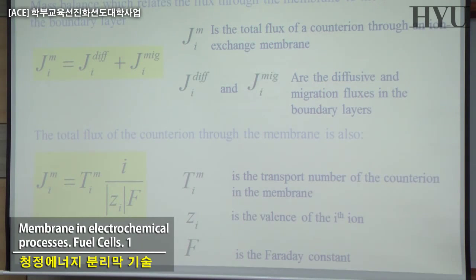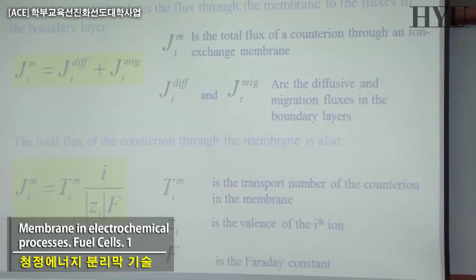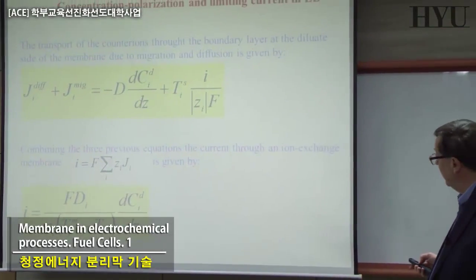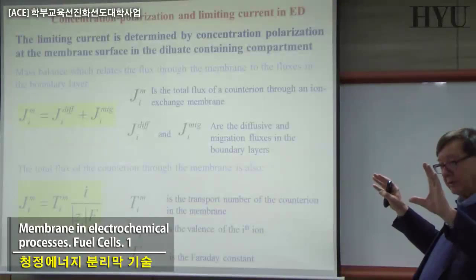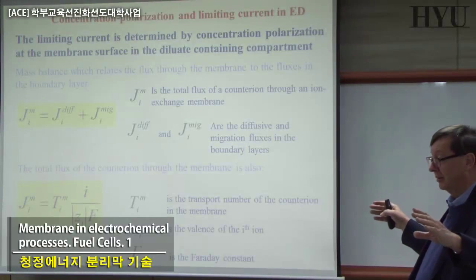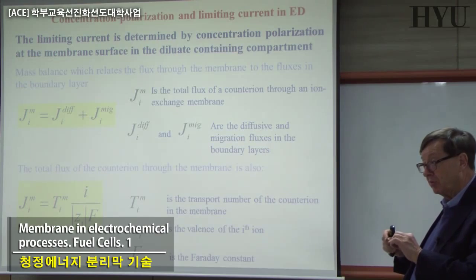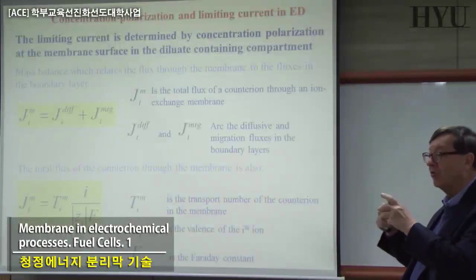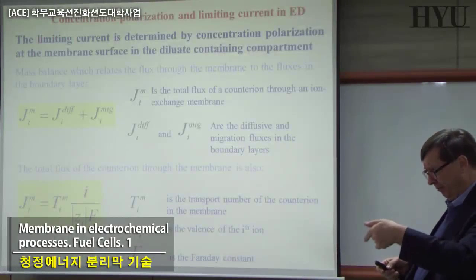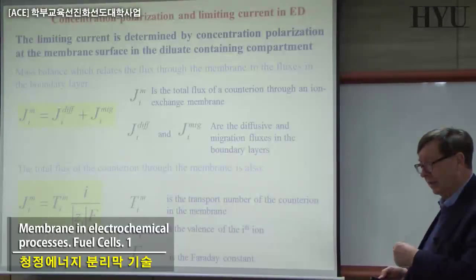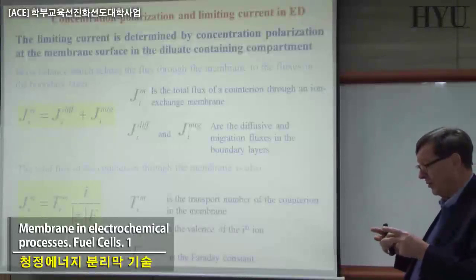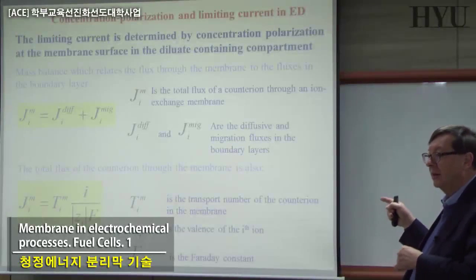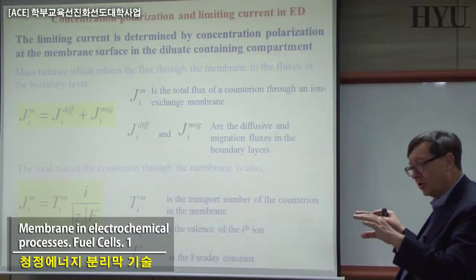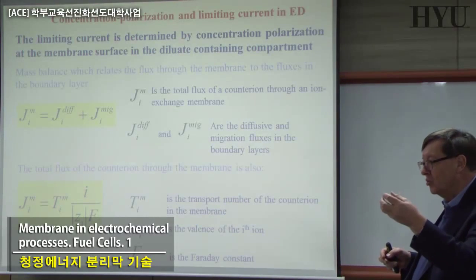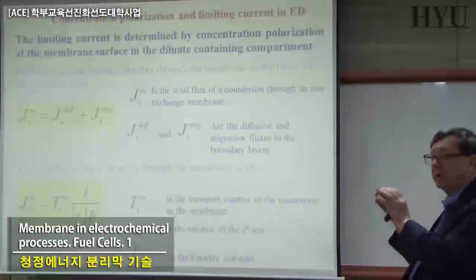And in the specific case that we are discussing of the ion exchange membrane, this is the transport number of the counter ion in the membrane. And you remember what it means. Ion exchange membranes are systems in which you have a polyelectrolyte, which is characterized as a polymeric system, where along the chain of your polymer there are some negative groups, for example, part of the chain, block, and some other ones positive that will neutralize the negative ones. Now the system is such that if you want to have two mobile ions, you have to break the chain, because the negative one in a negative polyelectrolyte is fixed, part of the structure. So we have one ion able to move and to counterbalance the fixed one. The other one, the fixed one, does not move.